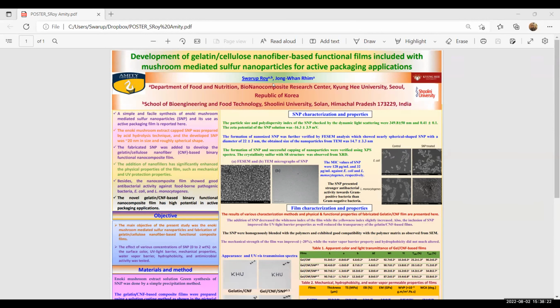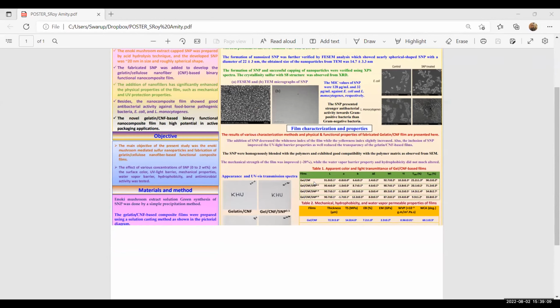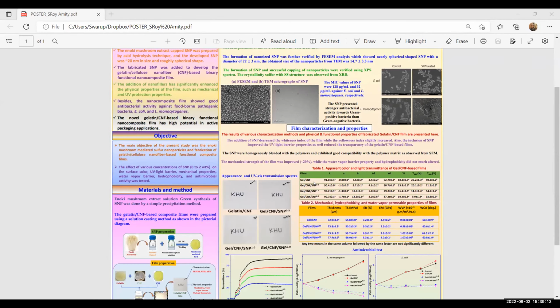So my work is about the preparation of gelatin cellulose nanofiber-based functional film by incorporating mushroom-mediated sulfur nanoparticle for active packaging application. So this work is about first synthesis of sulfur nanoparticle using mushroom extract. The sulfur nanoparticle can be synthesized by many methods. In this work, we used enoki mushroom as a source for green synthesis of sulfur nanoparticle. And that one is used for the fabrication of biopolymer-based film. And as a biopolymer, we used gelatin and cellulose nanofiber binary mixture. And then different properties of the film, which is required for food packaging application, are studied.